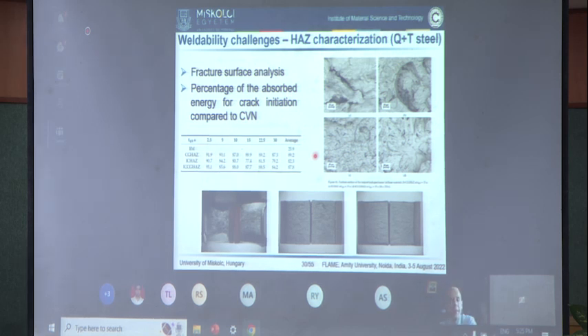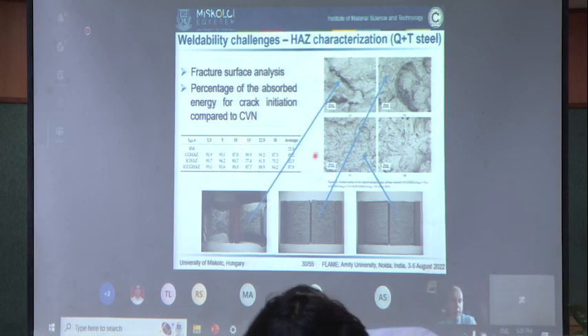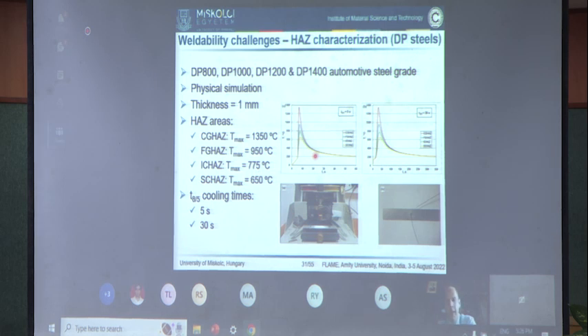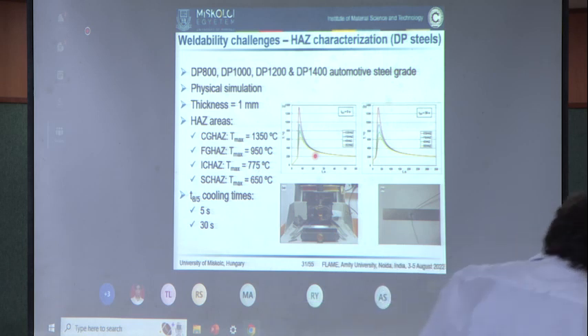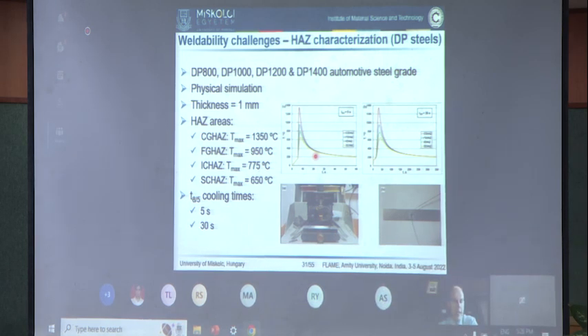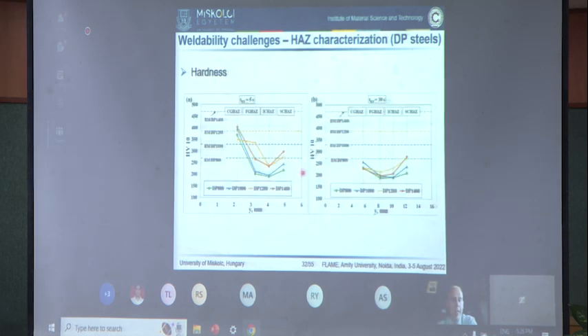Therefore, it's very important to minimize the extension of the heat-affected zone, because the heat-affected zone is very brittle in this kind of quenched and tempered high-strength steels. Besides quenched and tempered steels, we performed analysis on dual-phase steels applied in the automotive industry. From DP800 to DP1400, different grades were observed at 5 and 30 sec cooling time. In these dual-phase steels, hardening is relevant mostly in the coarse-grained heat-affected zone when low heat input is used, so generally 5 sec cooling time. But as we increase the cooling time, there won't be any hardening in the heat-affected zone. Furthermore, the heat-affected zone will rather soften.